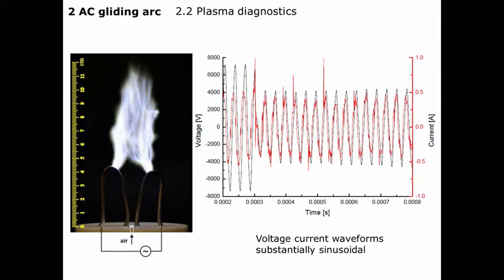We typically use nearly sinusoidal excitation with the voltage. Black is voltage, and red is current. We can see that current almost follows sinusoidal form, almost, with occasional, a little spiky stuff. So it's almost like DC resistance.